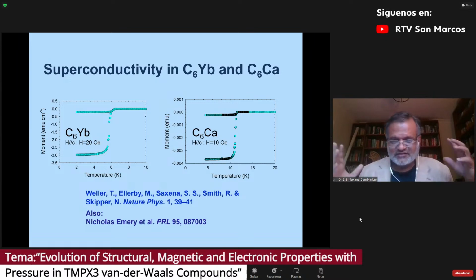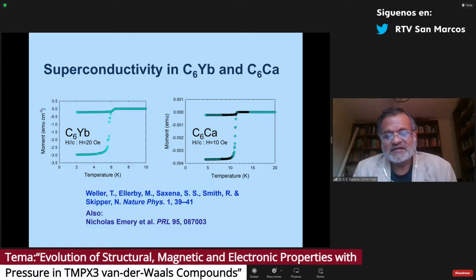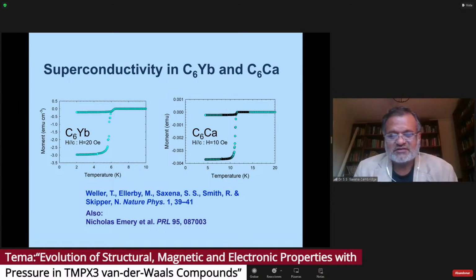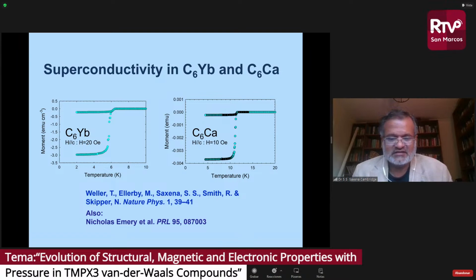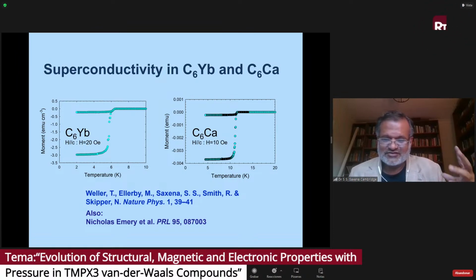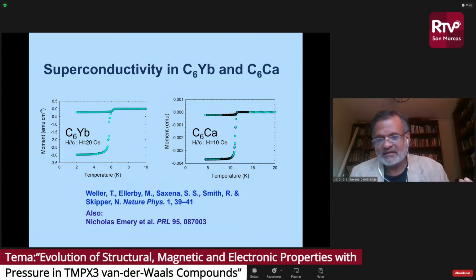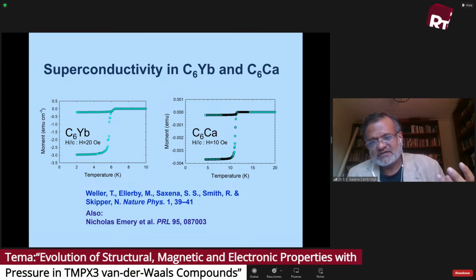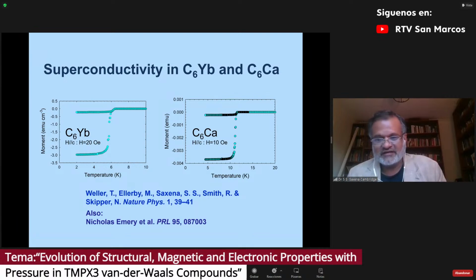But the initial euphoria about finding superconductivity in such a system was quite pleasant, but we couldn't actually understand what was going on, because when we looked at the magnetic data more closely, we found the ytterbium itself was not magnetic. It remained in the 2+ state and was not magnetic whatsoever. So the magnetism story that I built for you so passionately so far all of a sudden started to look less and less attractive to explain what happened here. To check that, we found that we can intercalate the system with calcium, which is not magnetic in any way, and the TC actually went up from about 6 Kelvin to 12 Kelvin. So this forced us to rethink the whole picture of quantum criticality and superconductivity in 2D in these kind of systems.